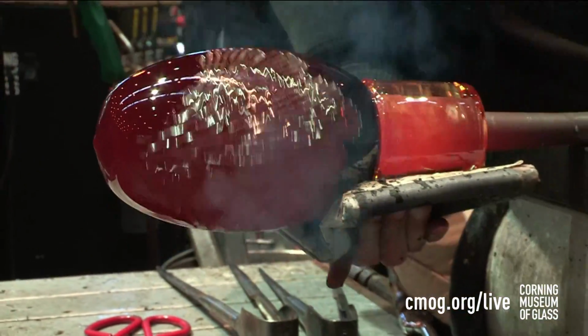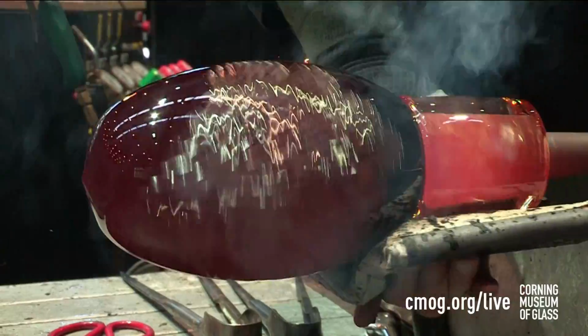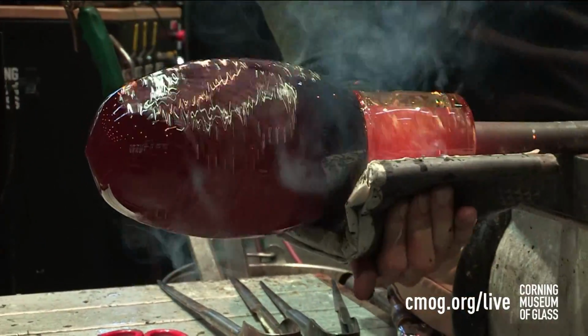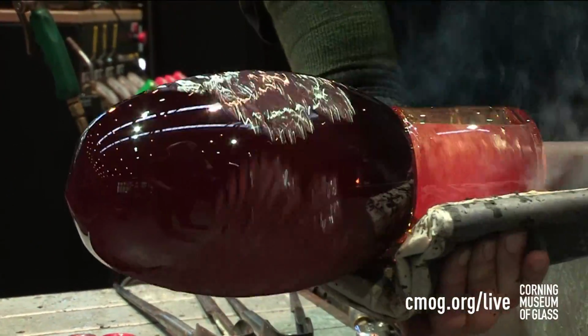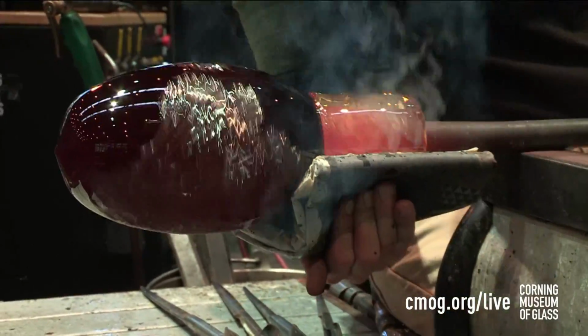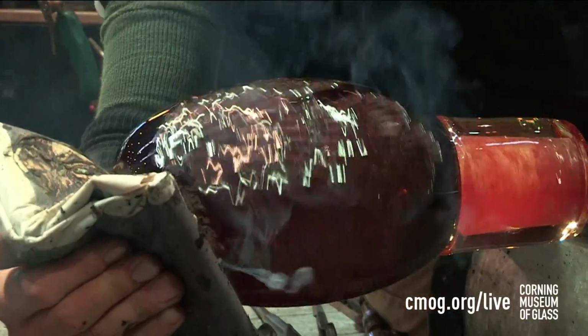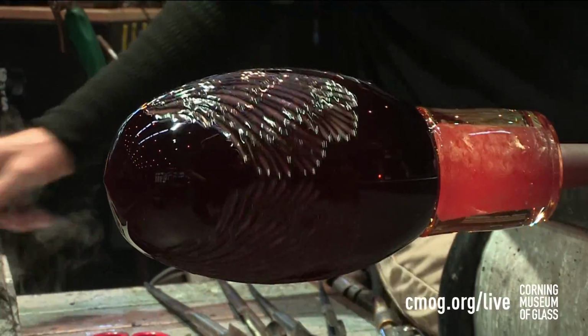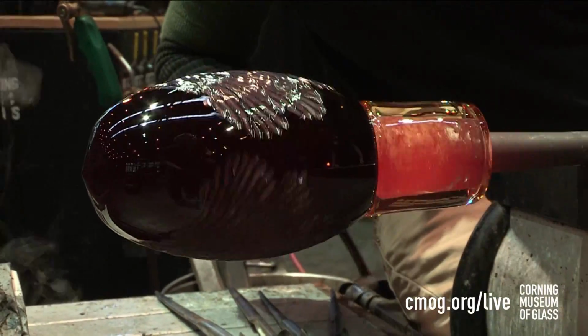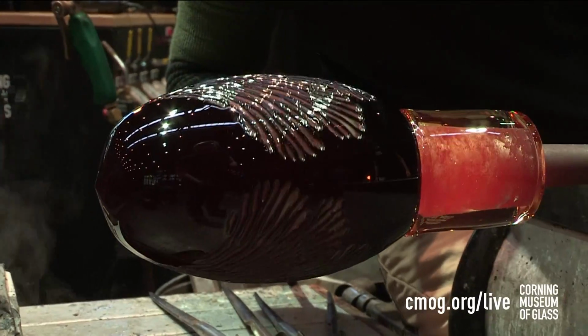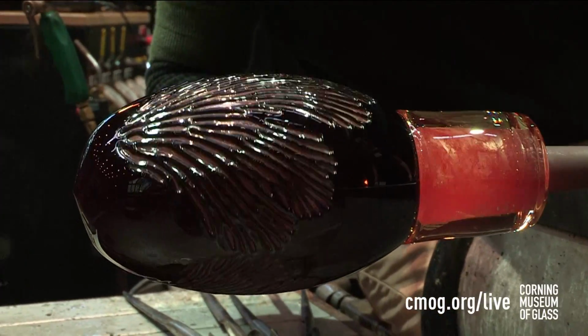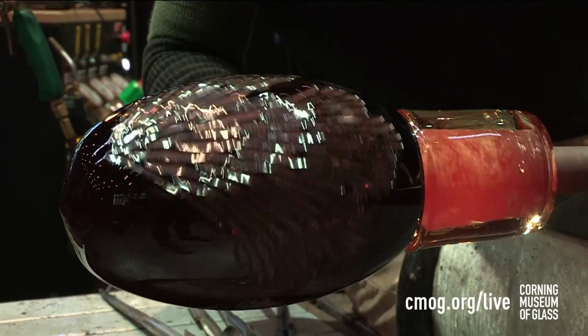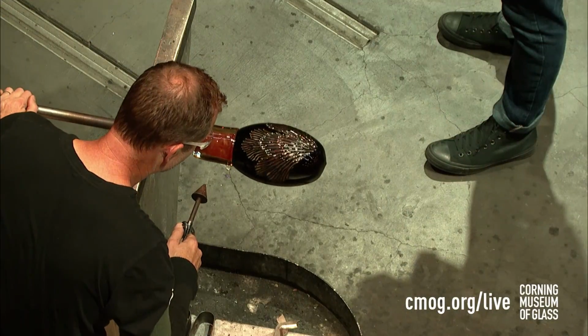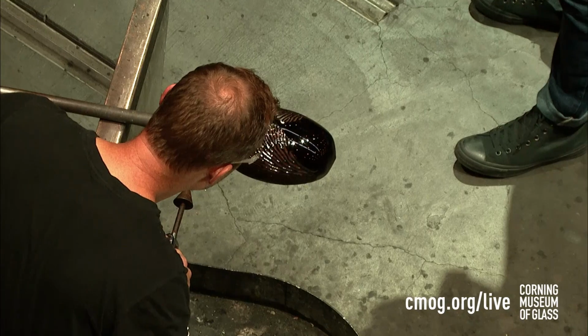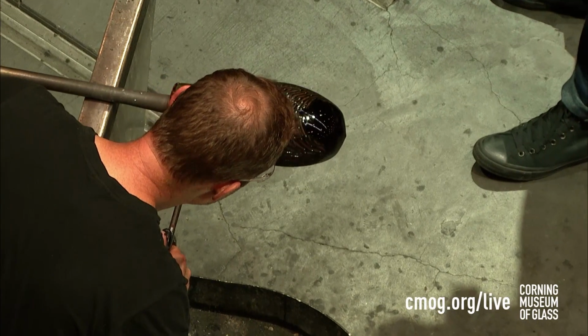So in the process of gathering glass, you go into a big pot in the side of the furnace, a big ceramic crucible that holds about 1,000 pounds of glass in this case. And if there's any little indentations or little ripples in the glass, it's going to trap a bubble. And so he wants to really smooth that out. So when Denise did the sandblasting, it actually created a little indentation. Yeah. And those grooves are pretty deep, they're not superficial. So I think that's what Eric's trying to do, is minimize the texture so that he doesn't trap lots of air.